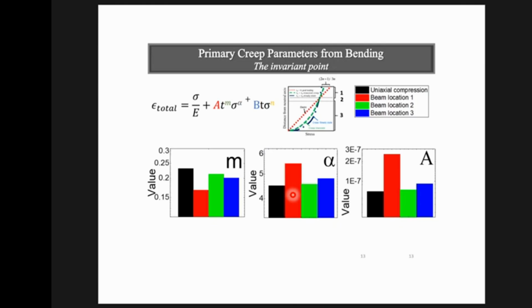And therefore, you're doing a uniaxial experiment at that point. And so by moving along the length of the beam at 2/3 of the distance from the neutral axis, you are getting multiple strain rate curves for different stresses.